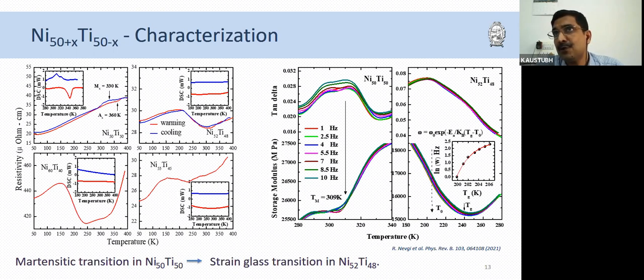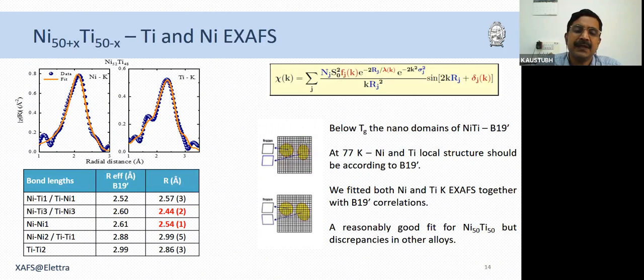Now, as I said, we wanted to understand the defect phase. XRD did not provide much information, so we thought we should do EXAFS. We recorded EXAFS, and these experiments were done at Elettra. When we extract the EXAFS signal, we want to fit it to this equation with a structural model. What we know from the previous studies is that the strain glass phase consists of domains which have martensitic order. So we thought B19 prime, the structure of the martensitic state of nickel titanium, could be a good model to start with to fit the EXAFS data.